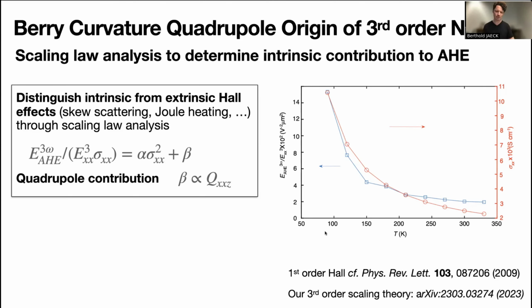Generally speaking, the expectation is that the intrinsic contribution to the Hall conductivity arising, for example, from Berry curvature effects should be temperature independent. And with this knowledge in our mind, we can then develop scaling theories to determine this temperature independent contribution to the anomalous Hall effect. In our case, for example, you can already pick this up when you look at the electric field ratios of the anomalous Hall effect versus the longitudinal conductivity. When you plot it, you can basically see that the amplitude of this ratio decreases, but picks up essentially a temperature-independent value as we go to larger temperatures. By contrast, the longitudinal conductivity does not show the saturating behavior towards larger temperatures, which is exactly what you expect for a metal. Now, just this plot already gives us a hint that there is an intrinsic contribution to this Hall effect, which we now analyze in the following.